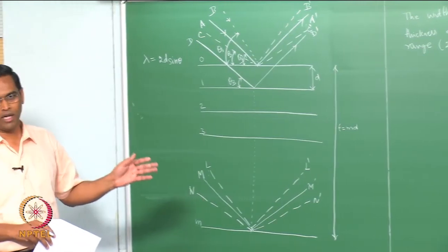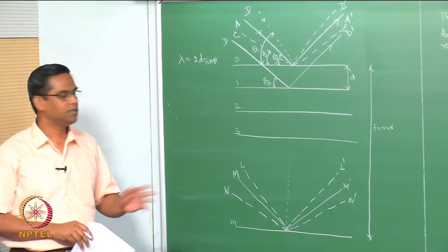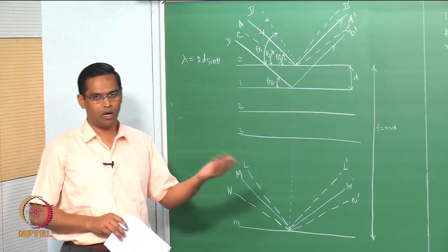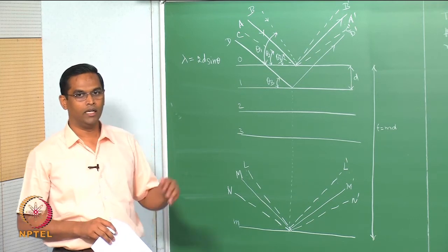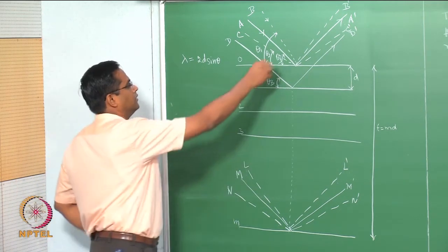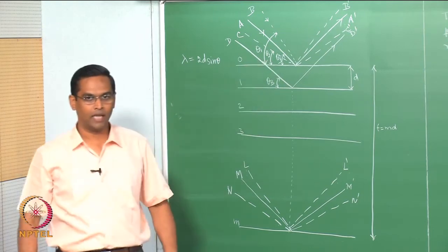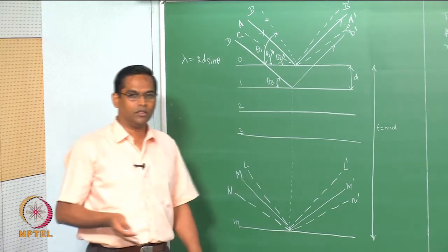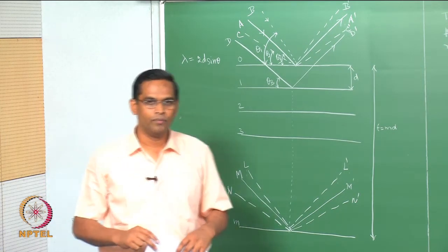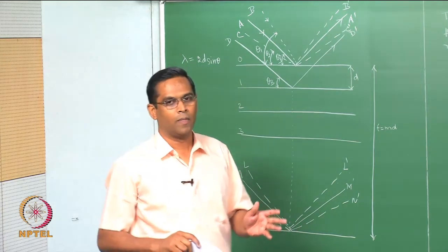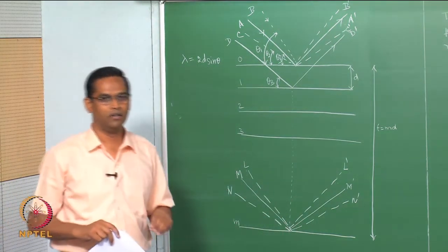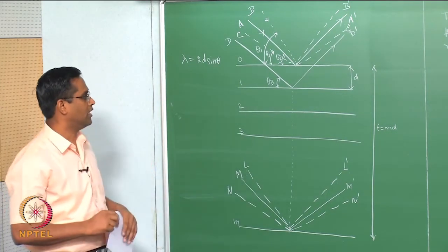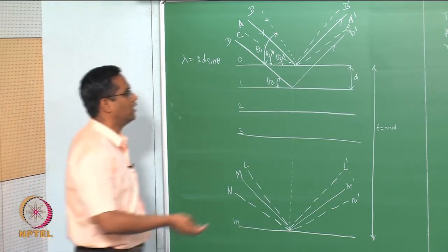One more point you have to recall, which we have already discussed in the last class: as the crystal size becomes smaller and smaller, and if we consider theta 1 and theta 2 slightly away from theta b, then the plane which is going to diffract with a half-wavelength phase difference may not exist. So that is another reason why we will see the peak broadening.